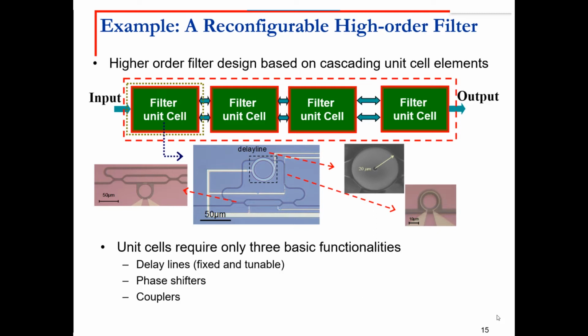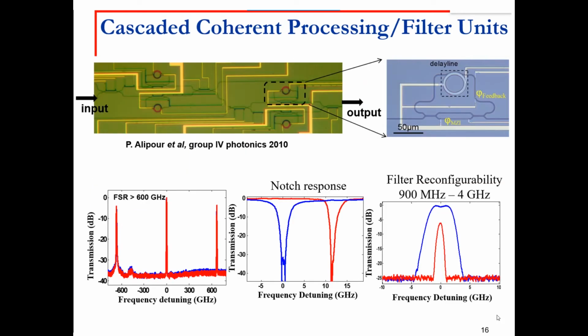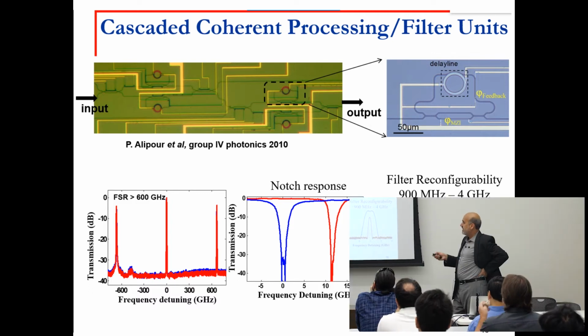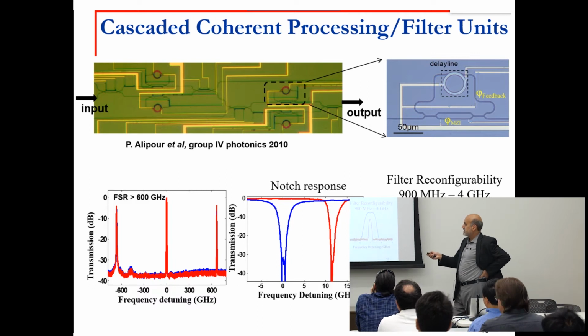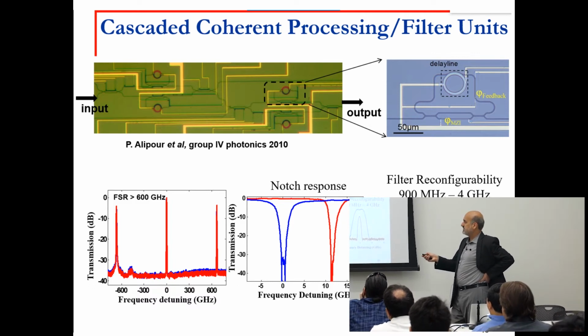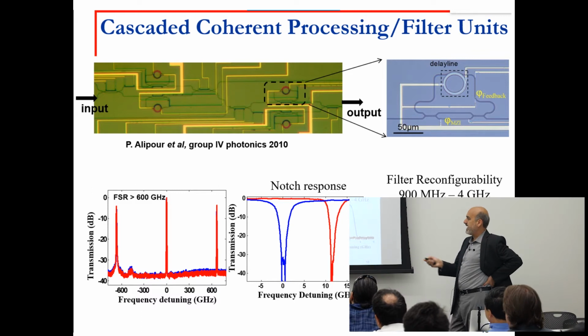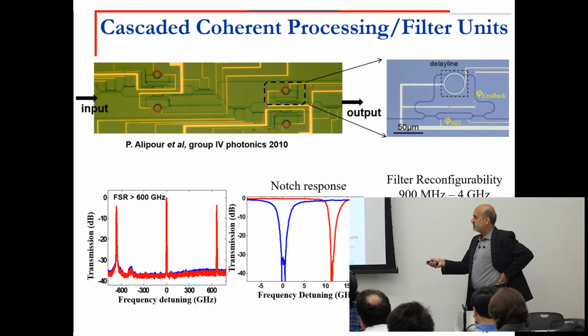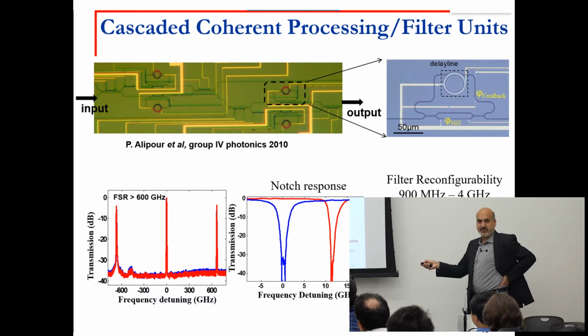This is an example of a fabricated structure. It's a fourth order filter that we fabricated at Georgia Tech. The key thing is that by applying heat through electronic means, you will change the functionality of the system. This is the same filter under two different inputs. It has a notch response or band reject response, and you change the wavelength that it operates at.